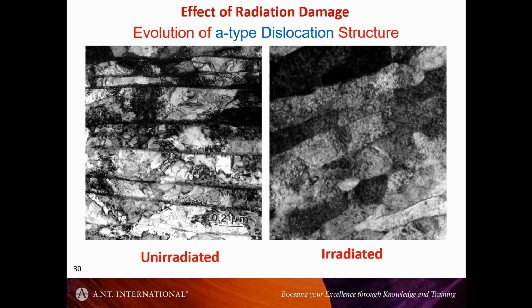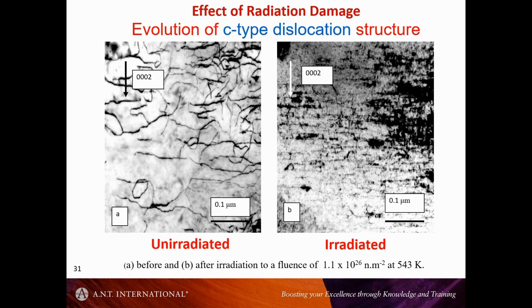Here's another example of the complexity of dislocation structures in materials, and also when you irradiate. In the Zr-2.5Nb pressure tubes, which I'm most familiar with, you have this small grain, high dislocation density structure, and then when you irradiate it, it just becomes even worse, because you're introducing all of these dislocation loops. And then when you look at the C component structure, which can be very complex, even more complex when you irradiate it, it all goes to the same end. You basically harden the material, which makes it much more difficult to deform.